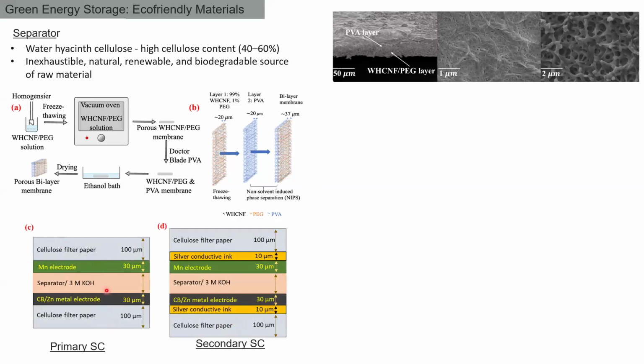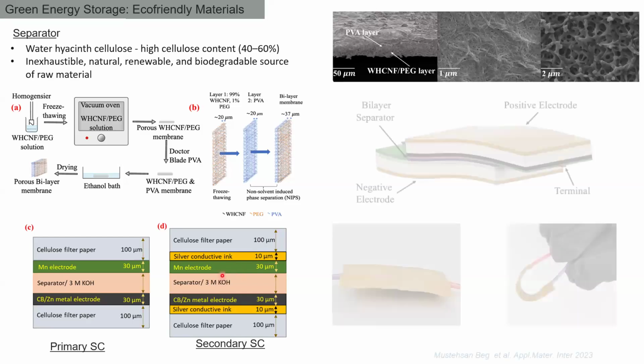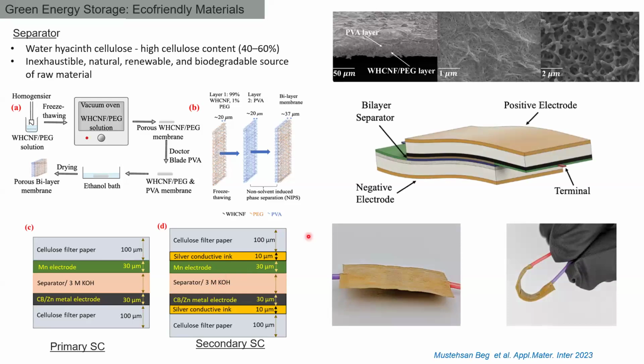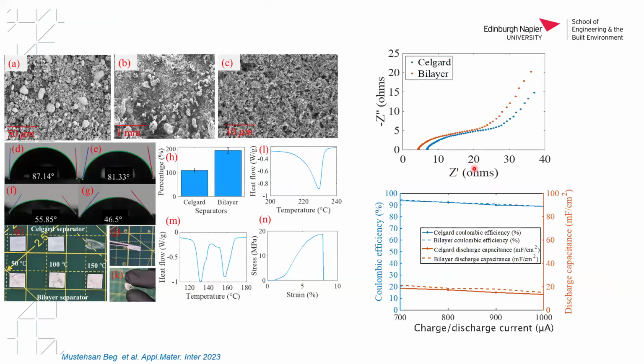Okay? The second, because this is a single use application, but if you want to use it for multiple applications, we used a silver conductor, and then used the electrode material on top of this. Then we observed the fabricated device, an ultra flexible one, with a copper-based electrode, and here is the electrode layer. When using the separator, on the top you can see the Celgard, and on the bottom our bilayer separator, the cellulose one.